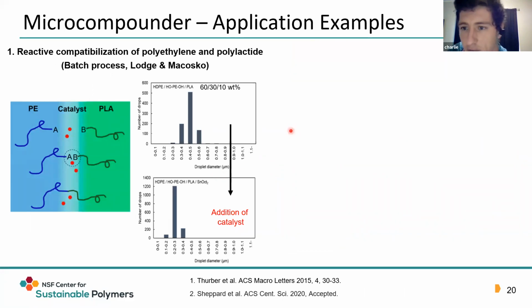Examples of microcompounding from the U of M: the first one is from the Lodge and Macosko group, in which a batch process was used. There they used reactive compatibilization of polyethylene and PLA blends, in which they added a catalyst, and because the catalyst was added, a reaction happened at the interface of the two polymers and formed block copolymers to reduce the interfacial tension, and therefore you could see the dispersion size decreased.